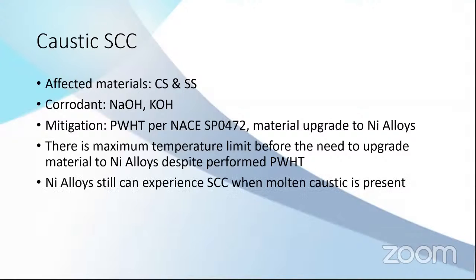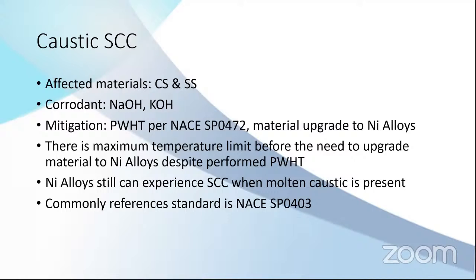But even if you upgrade to nickel alloys, you need to make sure that there is no molten caustic present, because they also can experience stress corrosion cracking when molten caustic is there. And you can see the NACE SP0403 to read about this caustic stress corrosion cracking. There's a list of other mitigation process over there. But what I said is just only for the weldments.